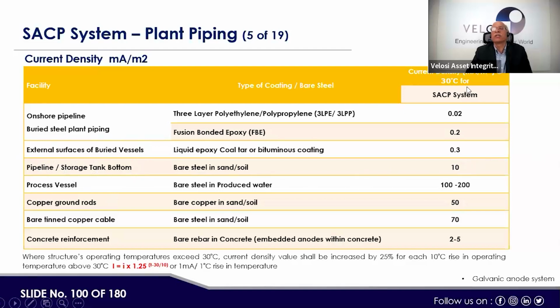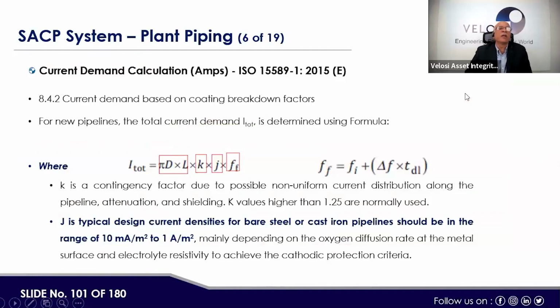So there are various current densities as per the SACP system. Then current demand calculations are done with this formula, which summary was given earlier. J is the typical design current density for bare steel or cast iron pipeline, which should be in the range of 10 milliampere per meter square to 1 ampere per meter square mainly.